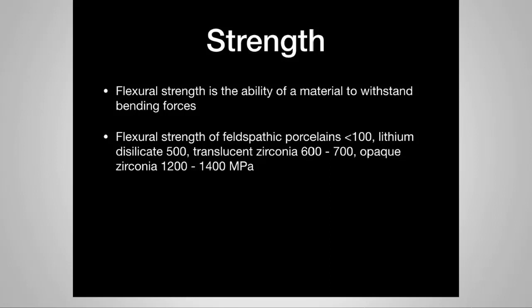Lithium disilicate, which is Emax, you can see that much higher than the feldspathic porcelains, right around 500 MPa. And then translucent zirconia, so that's on the 5 molar yttrium percentage. You can see that that's really not much more than lithium disilicate, so the 6 to 700 range. And then our opaque, which would be the 3 molar yttrium stabilized zirconia, is going to be way up. That's the bright white stuff that we're used to seeing at the 12 to 1400 megapascals. So keep these numbers in mind also.